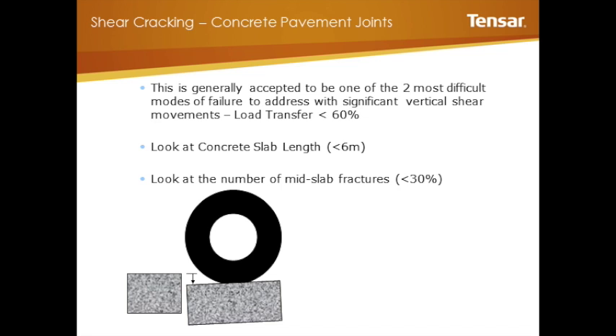Firstly, because you have to use a falling weight deflectometer to do it, or there is not a freely available technology to go out and do this. But let's say you didn't have that information available, then we look at some other indicators. One thing we've learned with experience, I think our first ever project with Glasgrid was on an 80-foot long slab. And it wasn't a real project, we just provided some materials for trials. And clearly the movement at that slab was so significant, because if you apply a very little load at one end of the slab, you get a high movement on the other. And so we've learned over time that typically slab lengths of 6 meters or less under conventional conditions would be an indicator for us that, hey, this is something we can handle, that the need to go and get data is less important, however, doesn't get ruled out.